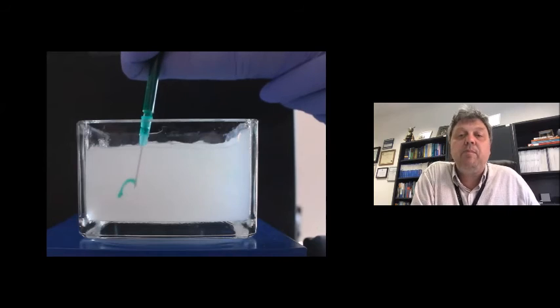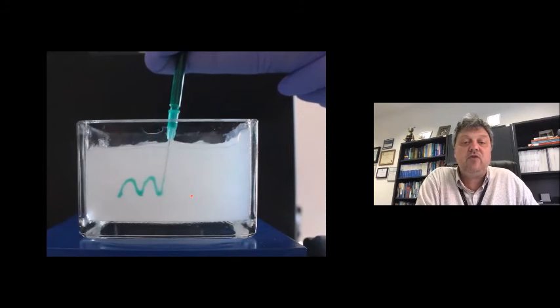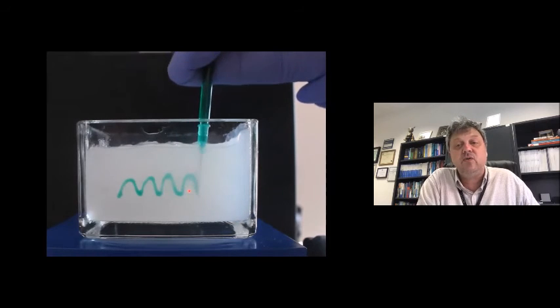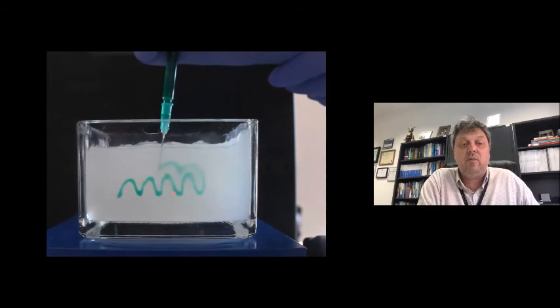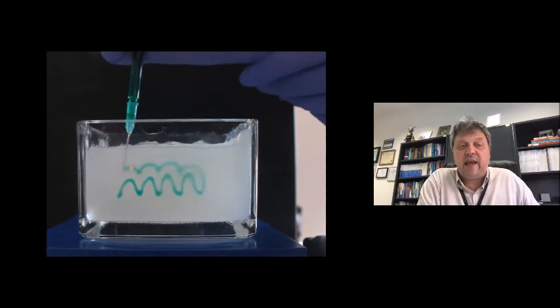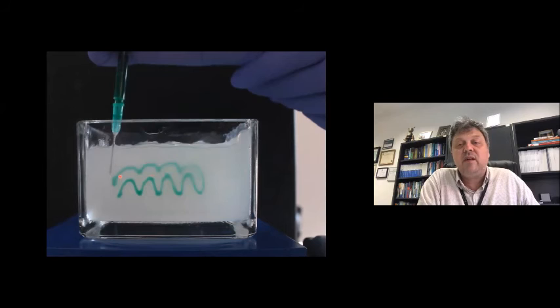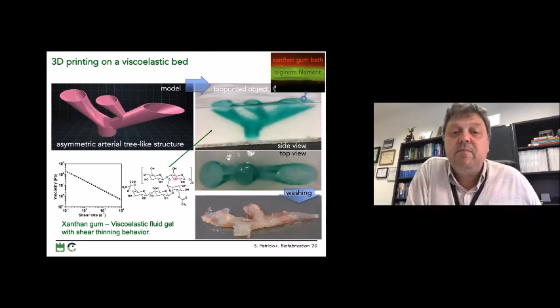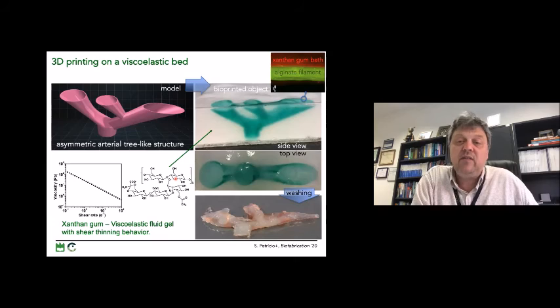So in our group, we developed a pure continuous viscous support that allows the fixation of complex centimeter-scale 3D constructs with arbitrary design, as you can see from this, not bioprinting, but hand printing. In this case, the green liquid is an alginate solution that is instantaneously cross-linked by the calcium ions that are present also in the supporting bath. So these are, of course, very simple structures, but we can process much more complex objects using bioprinting, such as this asymmetric structure that is similar to a vascular arterial structure that can be generated using a CAD model.